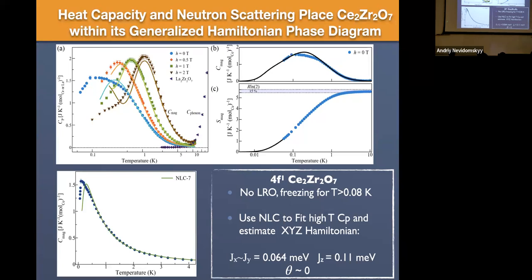So we have to account for R log 2 in entropy, and it has to go to 0. The only extra thing you could put in here in principle was to say, well, maybe there's a phase transition down here, in which case there'd be another peak. But actually there isn't much window in entropy for another peak. There's not much unaccounted for entropy.